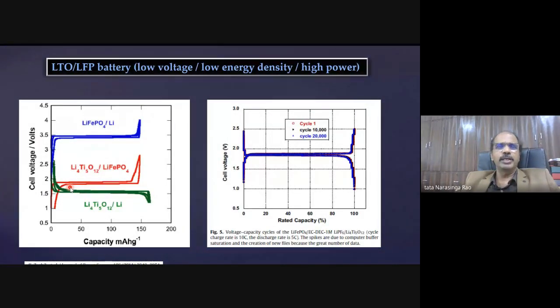So this is one, and then now you can see here LFP LTO. LTO means lithium titanate, I showed already, and LFP means lithium iron phosphate. And you can have this combination of battery to get a very good performance. What I'm showing here is it has a capacity of 170 milliampere-hour per gram, both the electrodes, 160 to 170. Then they're very flat. That means until you go this side, you can take the energy out and use it for your scooter, and until you take 90% of your energy, your voltage still remains constant. So your electric vehicle keeps moving.